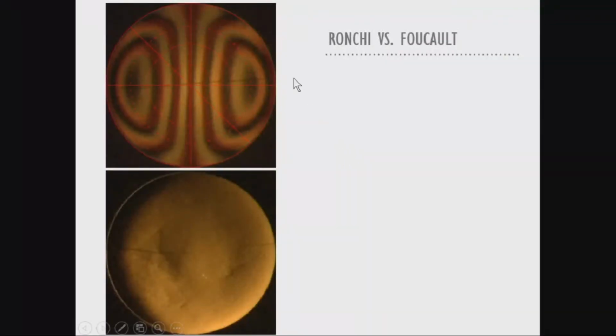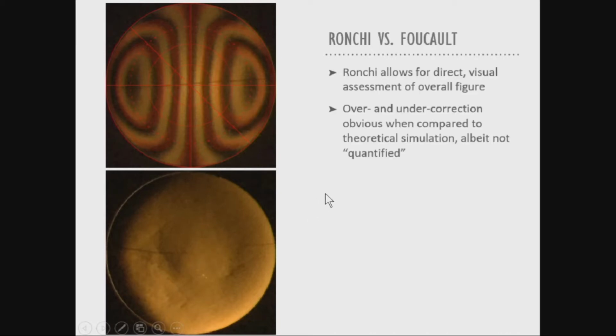So here's an example of the two approaches. This is a Ronchi image. The dark lines are what you see when you do the Ronchi test, and the red lines are the theoretical predictions. So basically, you look at your theoretical prediction, and you compare it to what you're actually seeing, and that will guide where you need to polish to get the figure that you need. Foucault, on the other hand, I guess I should have been doing this. While you can't quantify your errors, you can certainly see where your errors are. So you can see here the curve is not quite deep enough, and this is too sharp here. These are the qualitative things that you get from looking at this test.